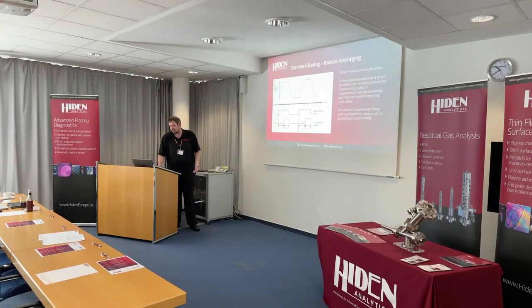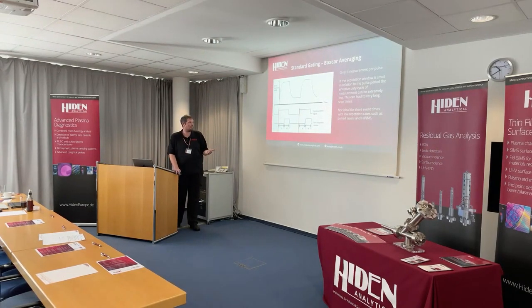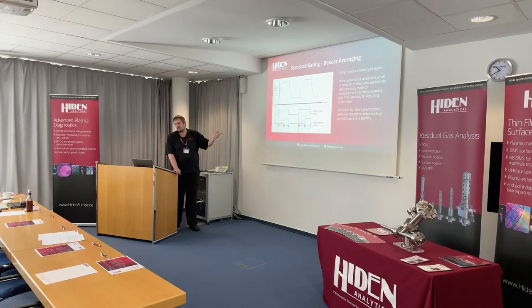So the standard gating that all instruments are supplied with, it's a boxcar averaging technique. So we supply the instrument with a synchronization signal at the plasma frequency, and then we choose a window of time within the pulse where we can acquire the data, and we can change the position and the width of the pulse with the two parameters.